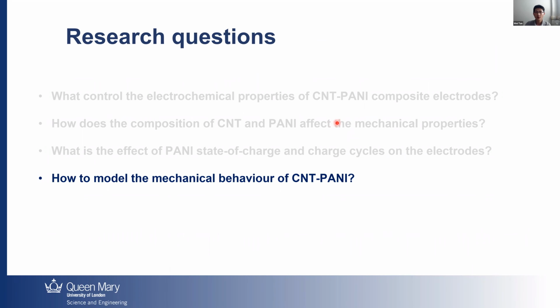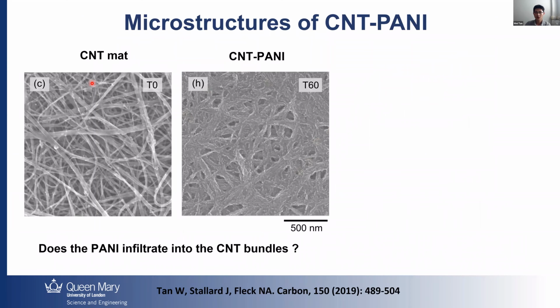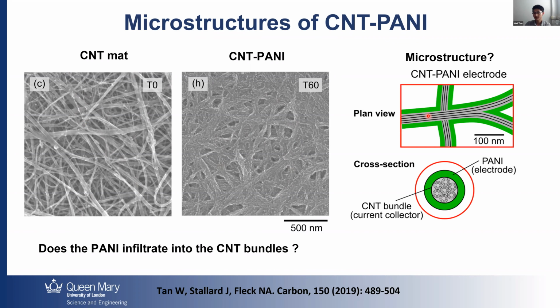The last question is how to model the mechanical behavior of CNT-PANI. So if you look at the microstructures of CNT-PANI, essentially the CNT mat is like this. After coating PANI, there's a very thick layer of coating on the CNT bundles. So we imagine the picture like this. You have the CNT bundle like these black lines, and you have the PANI layers just coat as a sheath of coating on the surface of the bundles.